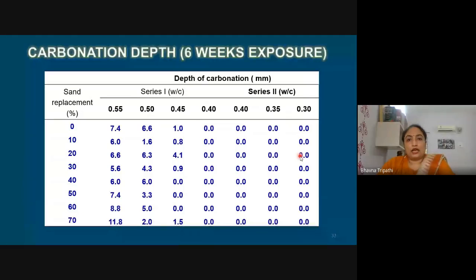Now, another parameter which was tested is carbonation. The depth of carbonation was tested at 1 week, 2 weeks, gradually up to 12 weeks. These are the results for 6 weeks, and I will not go into much detail, but what we can observe is that the carbonation depth of all the specimens having ISF slag is less than control, except for one mix which is the highest water cement ratio mix.